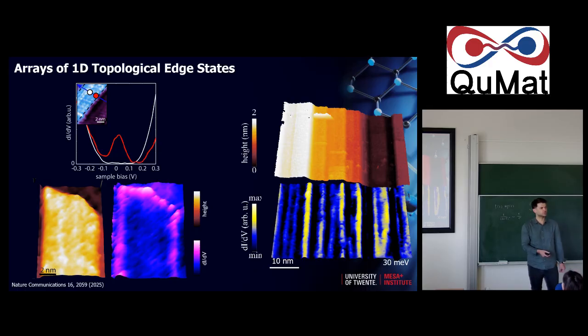What's causing the height difference between the difference? Yeah. The height difference here, you mean? Yeah. Yeah, it grows into like a step. So we think that it's coming from the substrate. So it's not that you have a bilayer germanene or multilayer germanene. It's a step height from the substrate. At least it's matching with the step height of the substrate and not with other germanene. So it's something that is probably coming from the substrate.